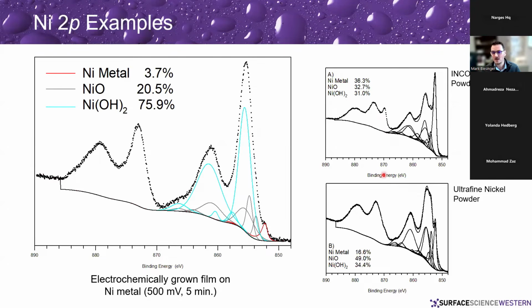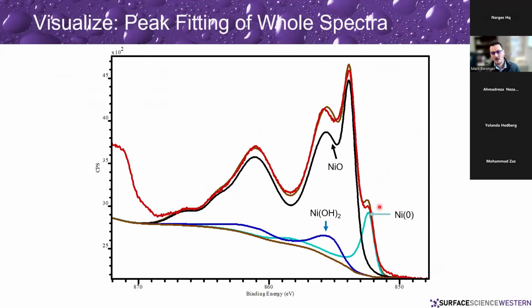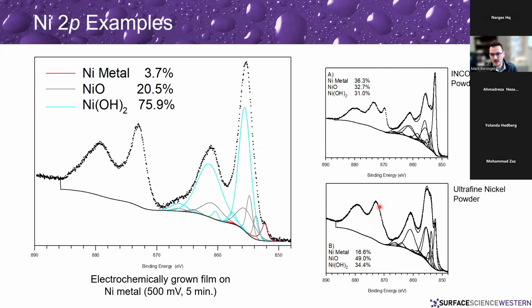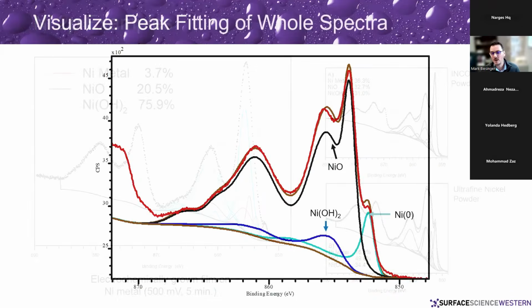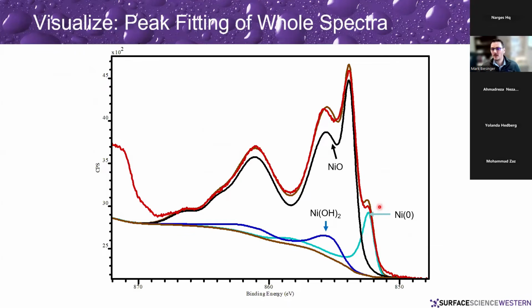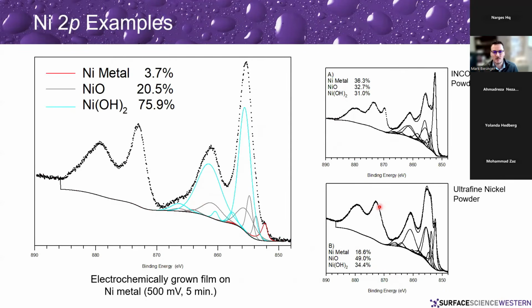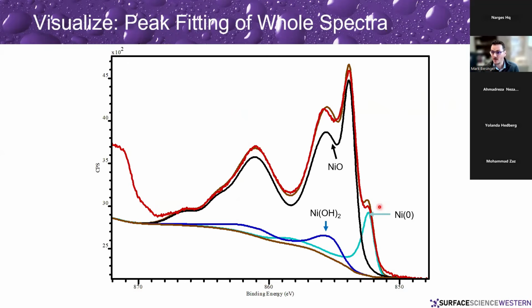And again, we have a number of samples here showing all these changes in peak structures and shapes, and being able to pull out how much of the different elements or species are present. If we visualize that, you look at this and go, well, that's a whole bunch of peaks just thrown under the curve. What does that mean? What we're doing is fitting whole spectra under these things. This is not a new thing to do. It is used in other techniques as well. And so we've started promoting this: instead of showing our spectra like this in our publications, we tend to start doing it like this, where we've added all those peaks together to show the spectral envelope that we're fitting here. And that just seems to be a little easier for people to understand that that's what we're doing here.